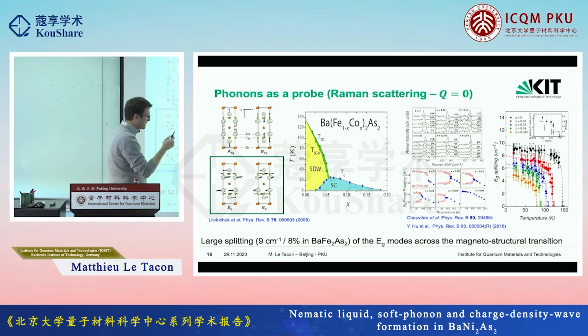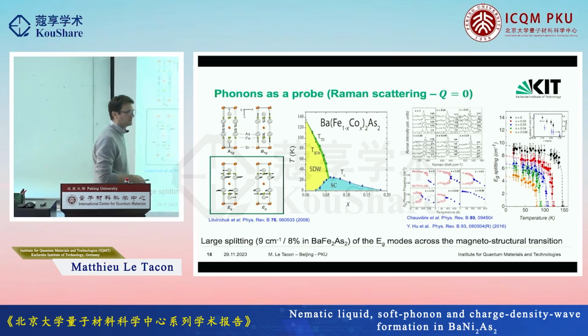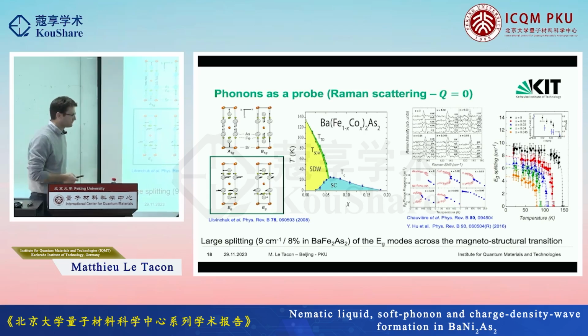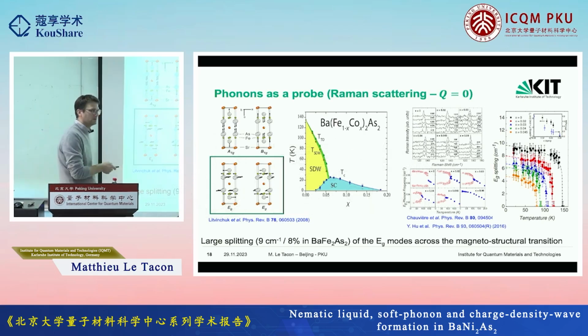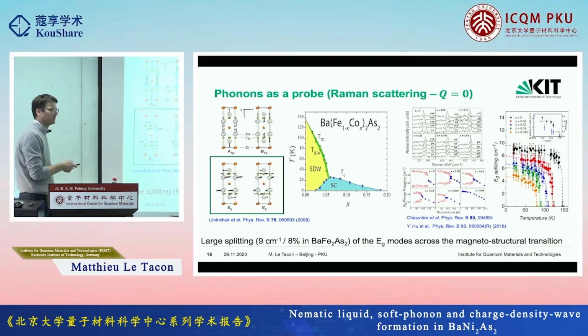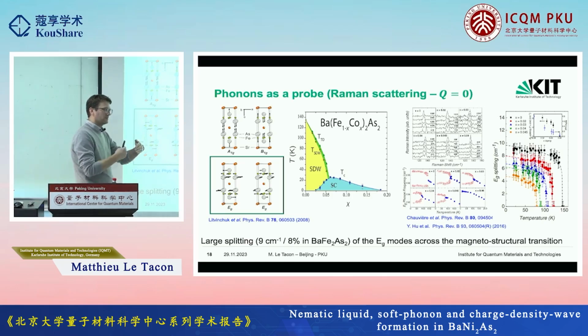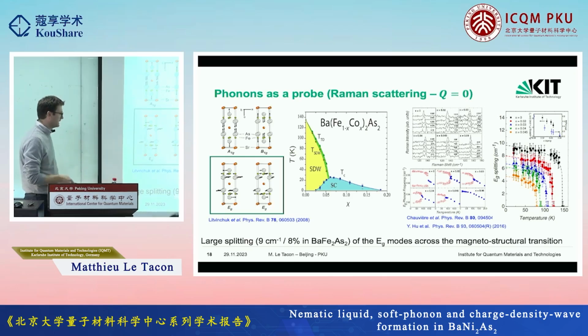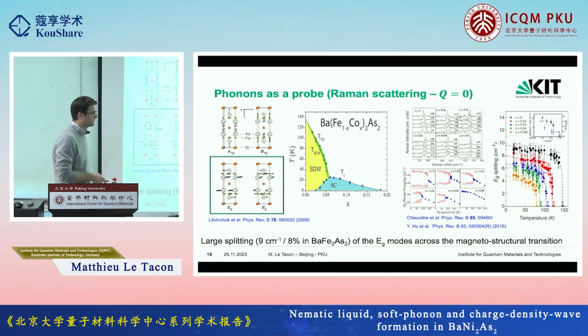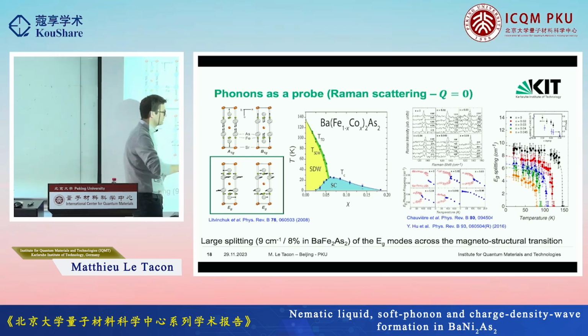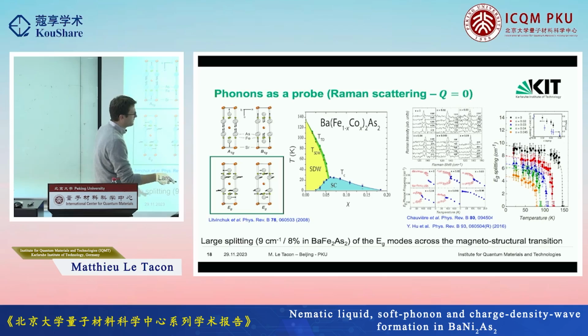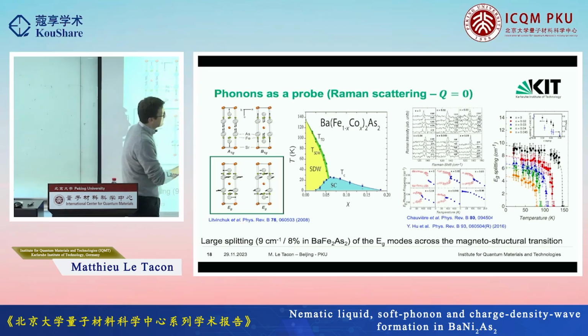And compared to the size of the distortion, this is actually a fairly large splitting. The distortion of the system is of the order of 0.1%. So you have 0.1% difference between the A and B lattice parameters, and it lifts the degeneracy of your phonon by 8%. So this was understood later on as a consequence of the coupling to the magnetic degrees of freedom. But what's interesting is that you can look at the temperature dependence of that splitting. So that's now the difference between the upper branch and the lower branch as a function of temperature for different dopings along the dome. And you nicely see this kind of order parameter-like shape.